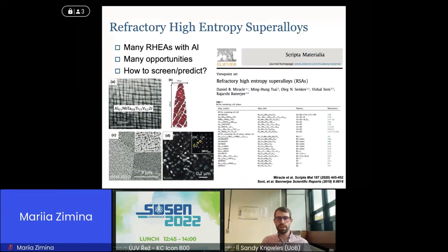So taking in the rest of the literature, we're not the only people to have pursued this BCC superalloy concept. So there are other systems, but none that have really reached commercial maturity. And hopefully there's a few different directions we could go in that maybe could get us there. One of the ones that's picked up quite a lot of interest internationally has been refractory high entropy superalloys. So this was a review paper, a Perspectives paper, just published a year or two ago. And at some of the major conferences, you're now seeing quite a lot more people looking at what I would call high entropy BCC superalloys. So you can get these gamma prime cuboidal sort of structures. So certainly something that's seeing widening appeal in the scientific literature.